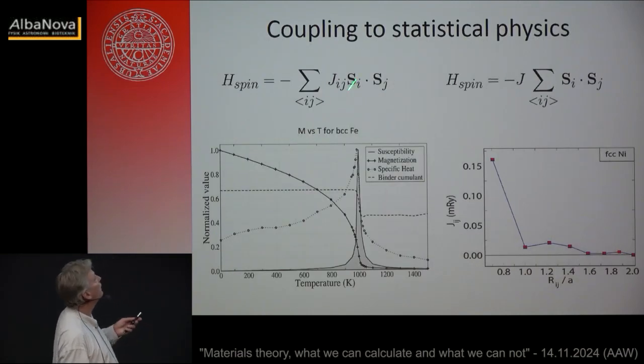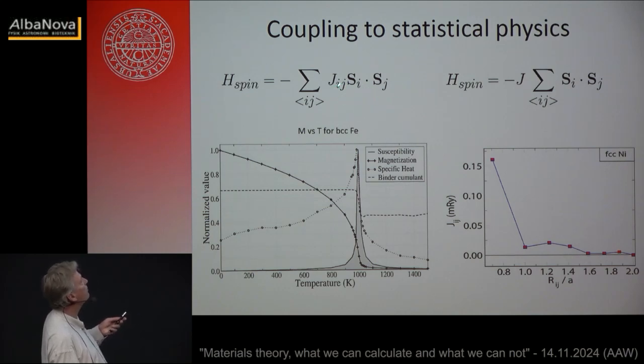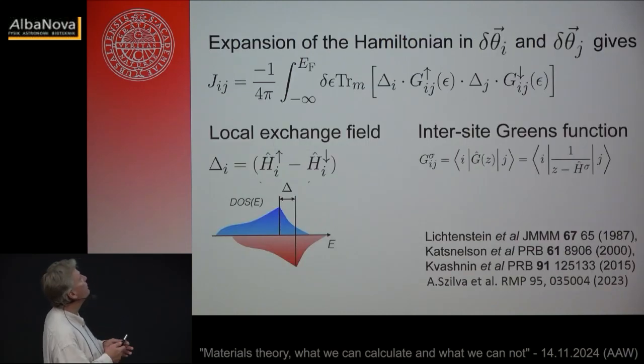And it's written up as this equation here, the regular Heisenberg Hamiltonian. This is the strength of interaction. This one determines if something is ferromagnetic or antiferromagnetic. And this Jij is now calculated from a local exchange interaction that I get from these density functional calculations.